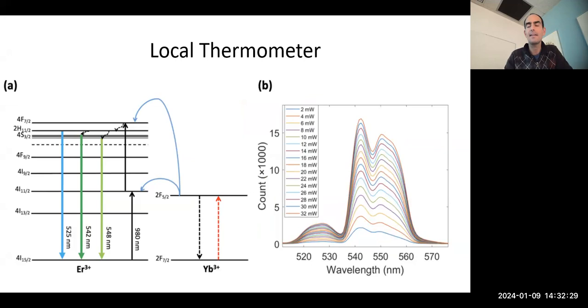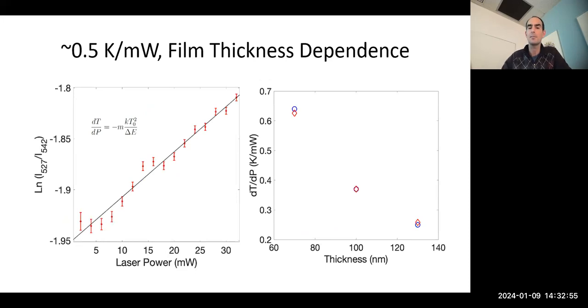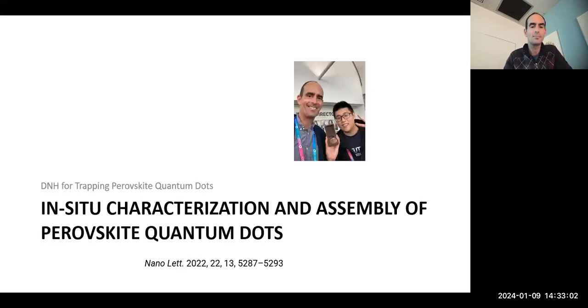Another nice thing about these lanthanides, which we've also been working on, is that by looking at the relative intensities of the different emission wavelengths of upconversion, you can measure the local temperature. From the Boltzmann distribution you can determine the temperature, and in these systems, as we heat by increasing laser power, we can measure the local temperature at the nanometer scale, which is kind of fun.